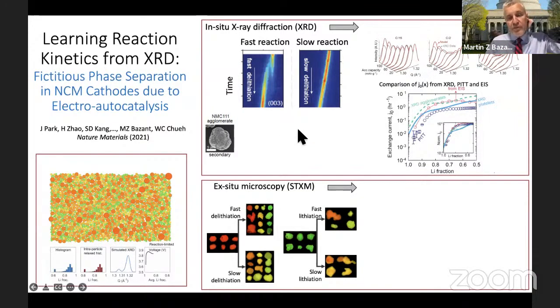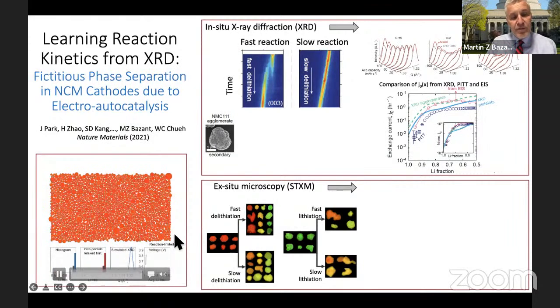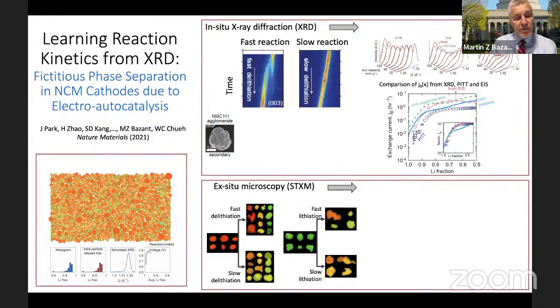And what we showed definitively in this paper is that this is a consequence, again, of this autocatalytic, autoinhibitory reaction rate for a material which is otherwise a solid solution material. So it's really the reaction rate nonlinearity that is destabilizing the system, but only during fast extraction of lithium. Below is a simulation of a porous electrode using our model. And here you see extraction. Red is the full state, and now we're emptying lithium.